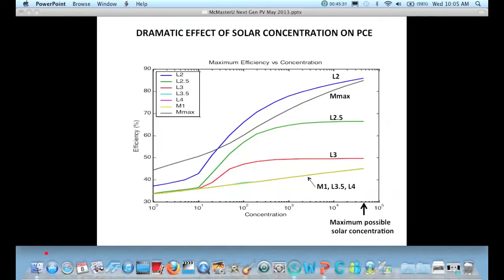But a normal solar cell or a quantum dot solar cell that has an onset that's greater than, say, 3.5, acts the same as bulk material. There's nothing to be gained there. The theoretical efficiency for a normal solar cell goes from like 32% at one sun to maybe 40% at, say, 500, or 42% at 500 suns. But a quantum dot with the staircase, or the L2, gives you efficiency of like 75%. These are theoretical thermodynamic efficiencies. So there's a huge gain in efficiency when you combine carrier multiplication or exciton multiplication with solar concentration. So this is a very important area to examine in the future.